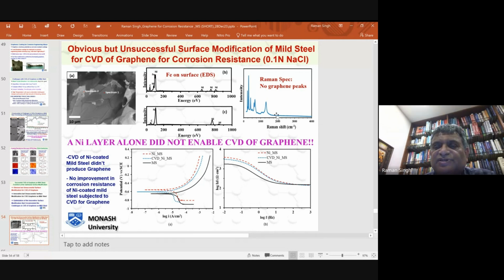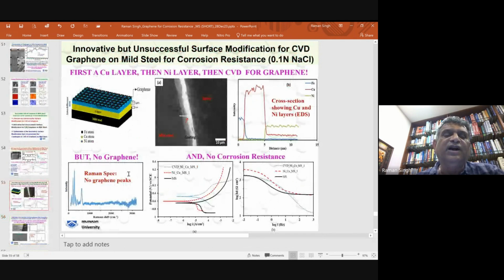Raman spectroscopy showed no graphene. Those G or 2D peaks are not there. And there's not much improvement in corrosion resistance, even if you put a nickel layer, because you lost all the carbon that you required for graphene development. So what you do, you want to stop carbon from diffusing. This is the top nickel layer. You don't want carbon to diffuse to mild steel.